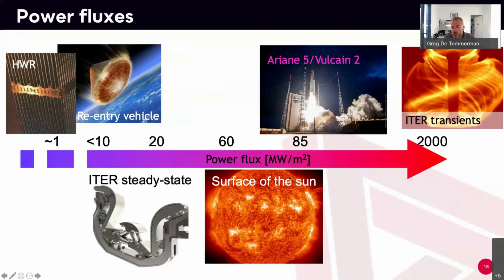To get higher heat fluxes in technologies, you need either to look at arc welding, for example, where you have very high localized heat fluxes. Or if you look in the engines of a rocket, you typically go in the 80 to 100 megawatts per square meter, but for a very short amount of time.